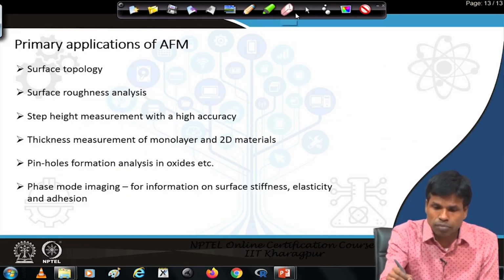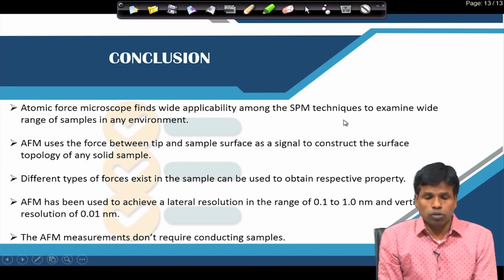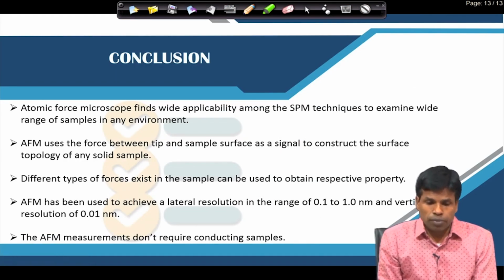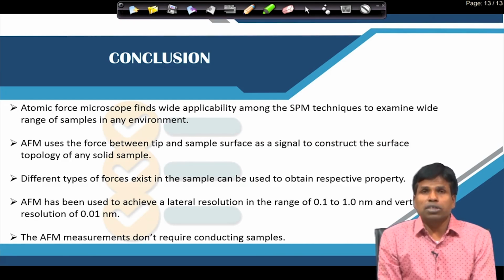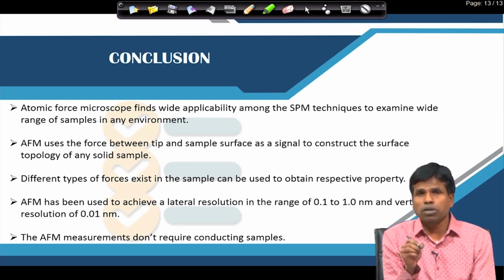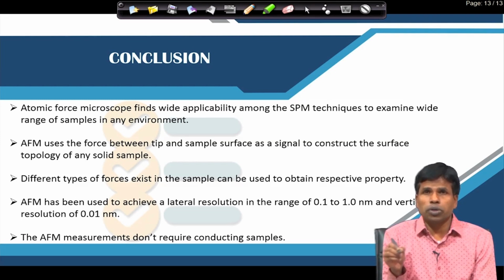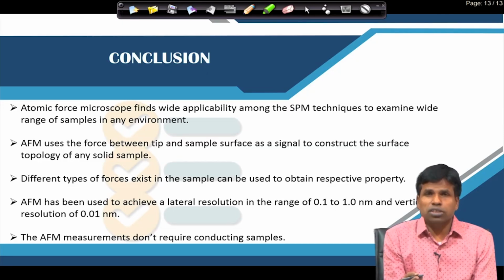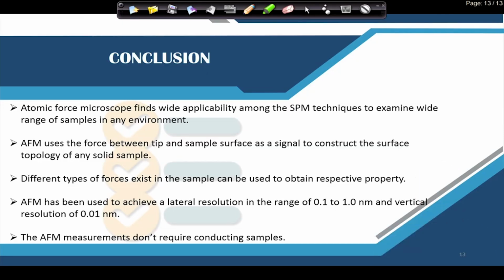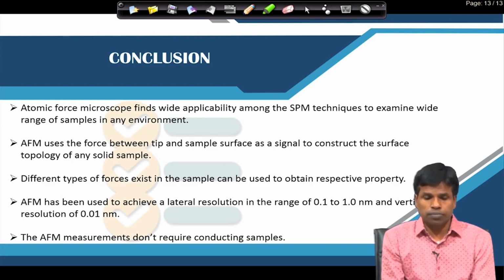So, these are the main applications of atomic force microscope, and in conclusion, what we see in this introduction is that atomic force microscope finds wide applicability among the family of scanning probe microscopic techniques to examine a wide range of samples in any environment, as here again a physical probe scans over the surface. Therefore, we do not need vacuum; we can use it in air, we can use it under liquid, like the scanning tunneling microscope. It measures the force between the tip probe and the sample surface as a signal to construct the surface topology. And as different forces exist on the sample surface, we can use the forces for measuring the respective property of the sample.